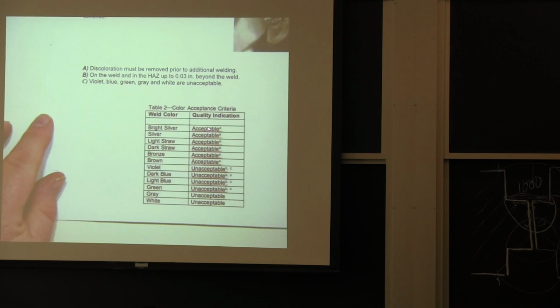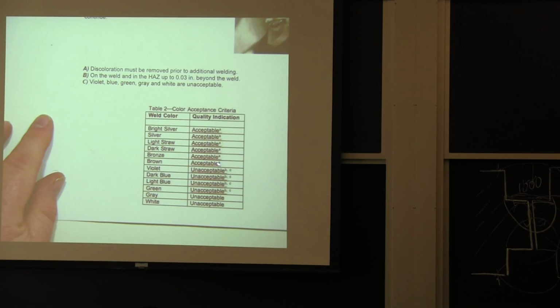The problem is it kind of goes through darker, darker, darker, cleaner, but dirtier further out. Okay? Right in here, you've gotten so dirty that the colors you're getting are because of the thickness of the oxide on the surface. Once your oxide gets very thick, you no longer get these interference colors, and it just goes back to its normal gray color. So people have tried for years, and this is something I got off the web, you look at the color and you find out whether the quality of the weld is acceptable.